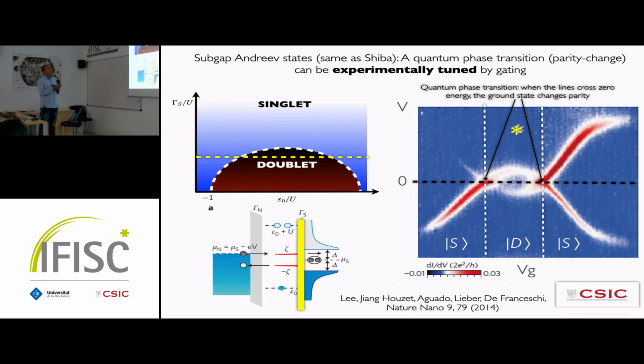So here, when you are in the singlet, you see this line. This is essentially the gap of the superconductor. This line lives near the gap. But as you start to change the gate voltage that you apply in the experiment, which is essentially moving the level position of the dot, you start to see how these two lines, and these are the electron-hole symmetric lines that you wanted, Llorens, these are the electron-hole lines, go to zero. They cross zero energy here.